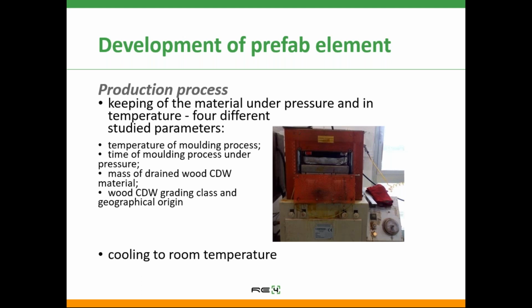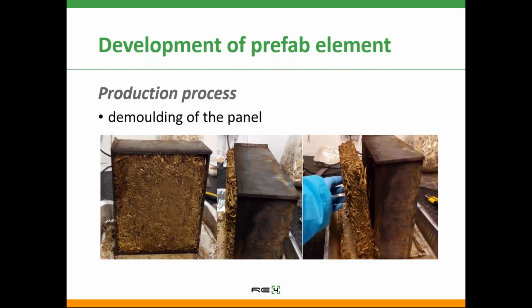The wood insulating panels production process was defined through 4 different parameters: the temperature, the time of the molding process under pressure, the mass of dry construction and demolition waste wood material, and the construction and demolition waste wood grading class and geographical origin. After this step, a cooling to room temperature step was realized, where the mold was removed from the press at the steaming temperature and then cooled down to room temperature. Finally, there was the demolding of the panel, where the panel was removed from the mold.